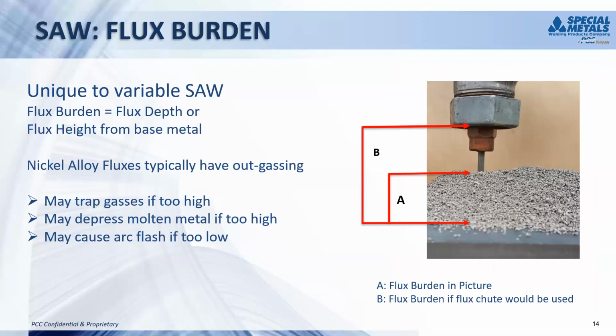One of the biggest problems that I see coming up when it comes to nickel welding is the flux burden, or the level and the height of the flux that's used. With steel, it doesn't seem to really bother it if you just completely bury the arc. If you ever see flash, you'll see guys have scoops, just throwing more flux onto the weld to cover everything, and it doesn't really seem to cause any problems.